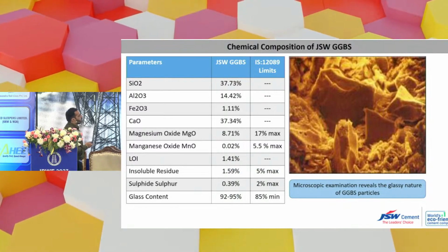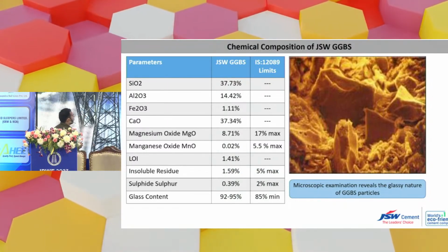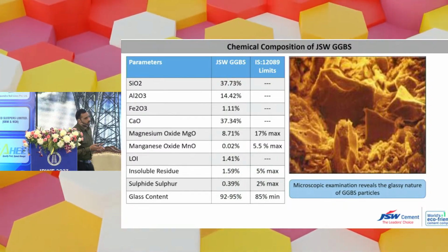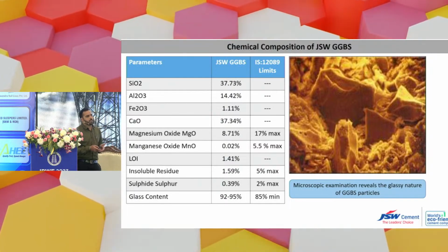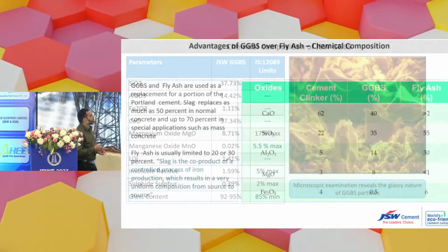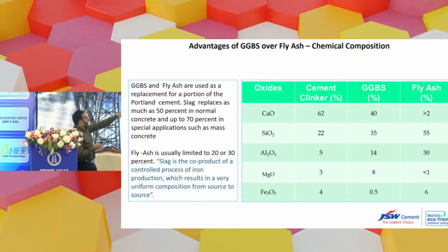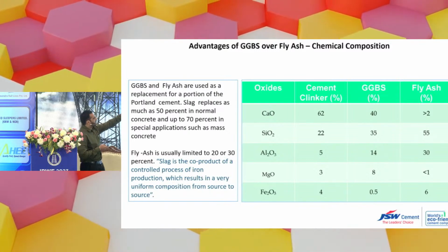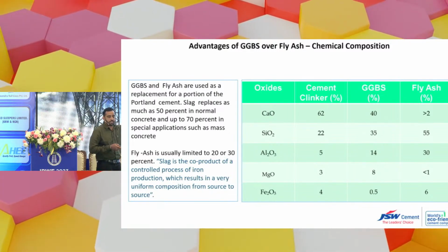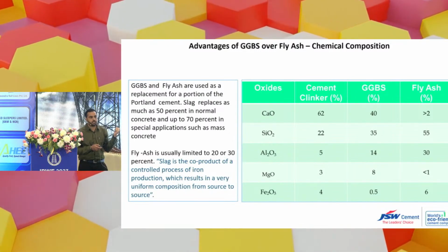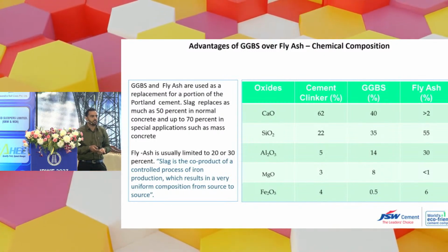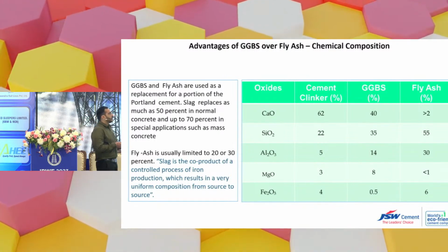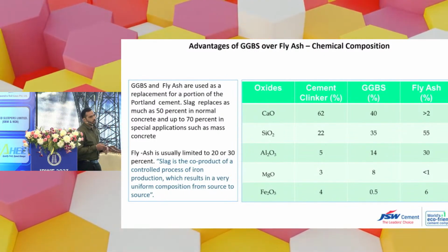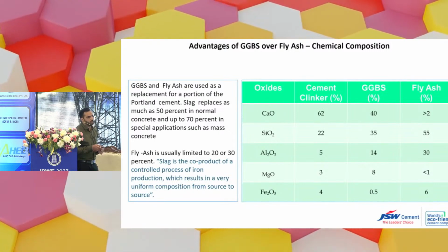These are the chemical compositions of GGBS. It has silicon dioxide around 37% and calcium around 40%. It comes from the cement family only. If you see the chart, it has a lime content around 40%, whereas cement has a lime content of 62%. That's why we say the product is related to the cement family. Fly ash has only 2% lime content, which is what reacts with the water.